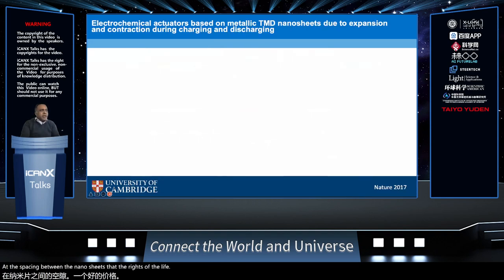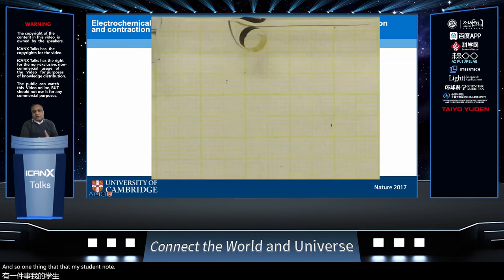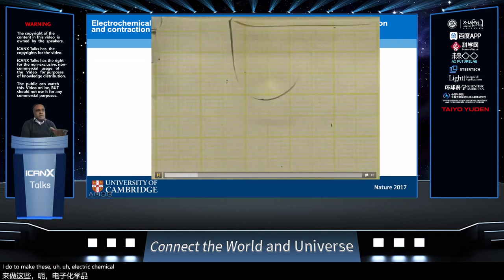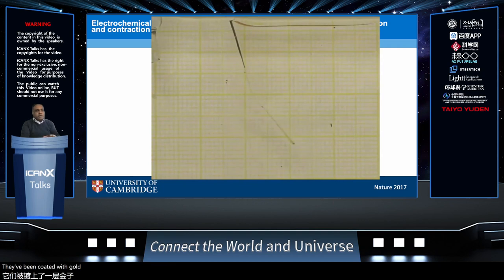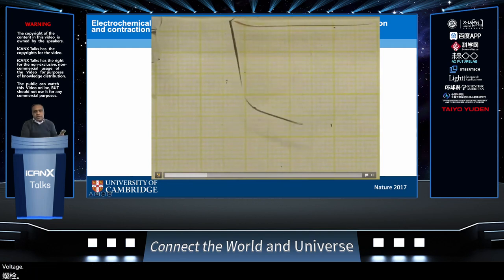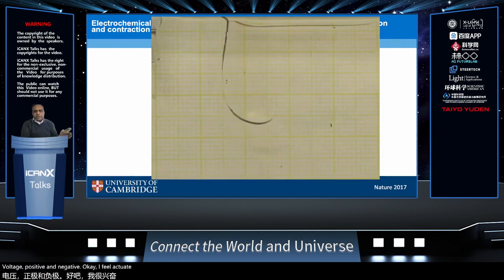that gives rise to the large capacity. And so one thing that my student noticed when he was doing the supercapacitor measurements was that these restacked electrodes are able to expand and contract quite dramatically during charging and discharging of the electrodes. And so he utilized this to make these electrochemical actuators. So this is basically a freestanding 1T phase MoS2 strip that's been coated with gold. This is immersed in electrolyte, and he's applying positive and negative voltage to actuate the strip.